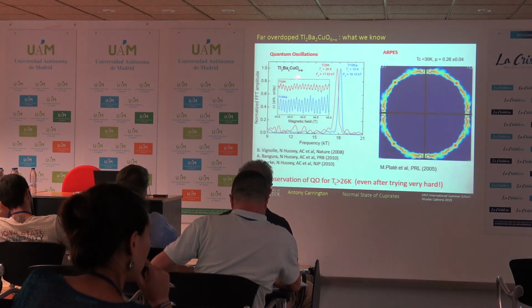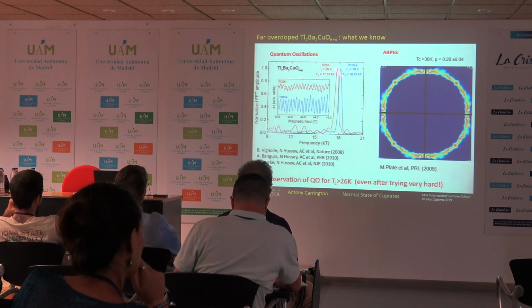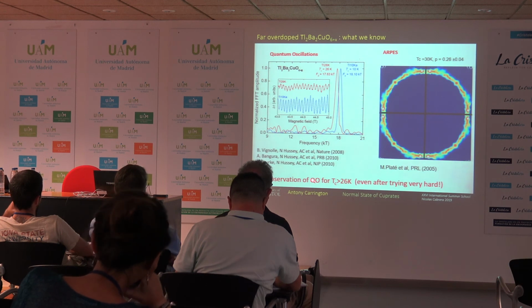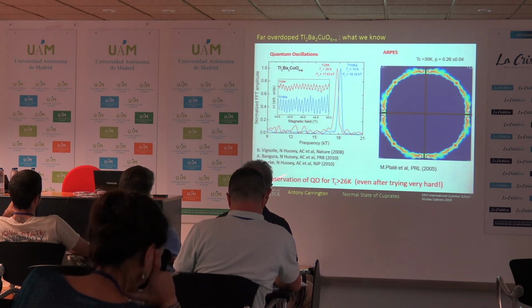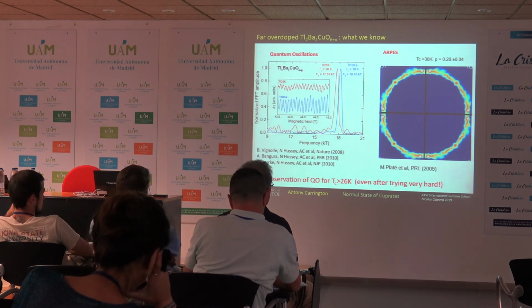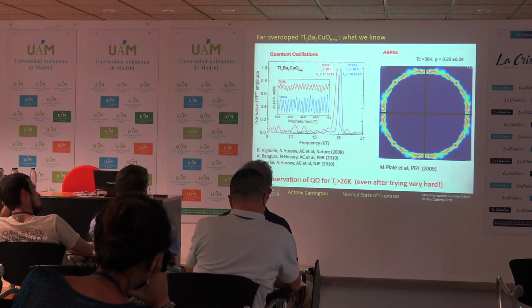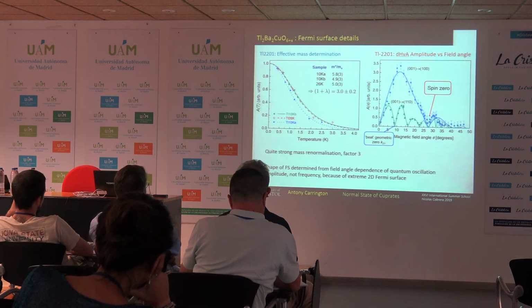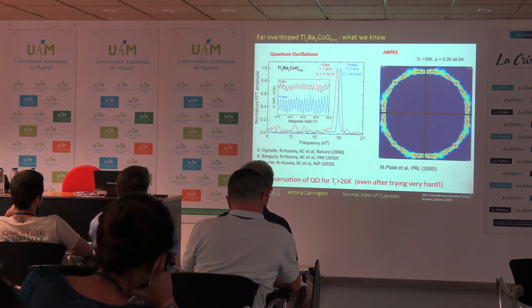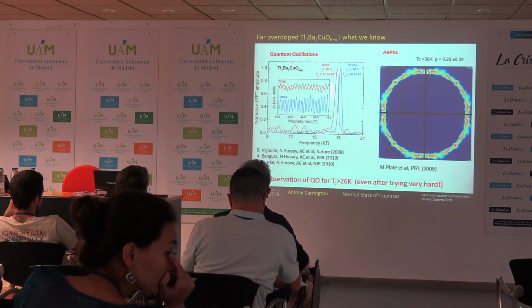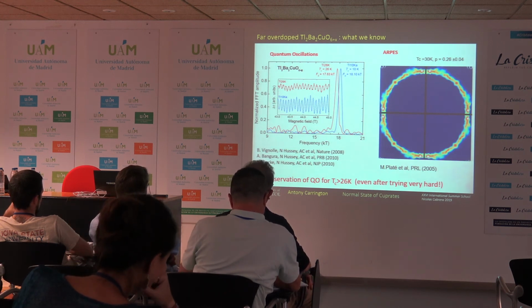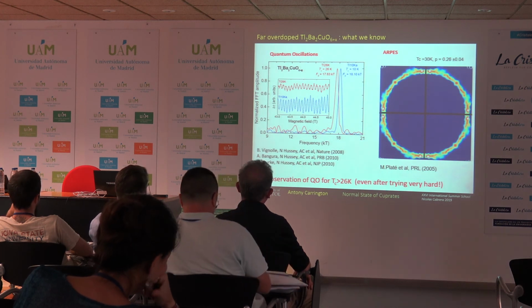We first of all discovered quantum oscillations with a very overdoped sample of TC of 10K. And then we spent a long time, many years, trying to find quantum oscillations in higher and higher TCs. I think we measured something like 60 or 70 samples in pulsed field in the end. And we found success only at 26 Kelvin. That was the highest TC we ever saw quantum oscillations in. Okay, so keep that number in mind for later. Interestingly, if you compare the data for the 10K and the 26K, it's not actually significantly different in terms of amplitude, given the fact that there are often these exponential damping factors.